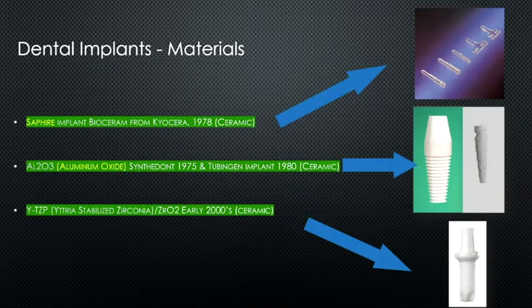That's the Synthodont that was made by Bicon in Boston, started in 1975. And that's the famous Tübingen implant, which I said gave a really bad name because it had a tendency to fracture here right at the neck. And it was made of aluminum oxide, which is very rigid. It doesn't have flexibility. So there were a lot of fractures, but also a lot of failures because all these three implants had surfaces that were pretty smooth. This was the smoothest with the highest failures. These were pretty smooth. This was also smooth, and you tended to have a higher failure rate.